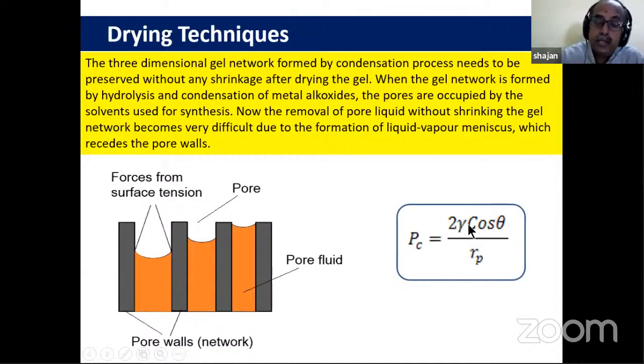So the only factor which I can use here is the interfacial surface tension. If I can reduce the interfacial surface tension, then automatically I am reducing the capillary pressure. So in that case, you have to retain the pore diameter. You should not disturb this. Only one thing you have to play with, this interfacial surface tension, and automatically the pore capillary pressure will reduce.